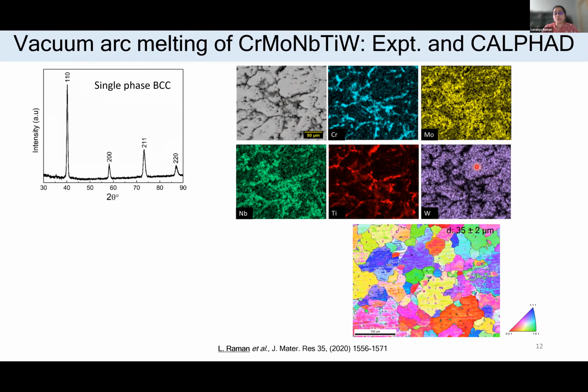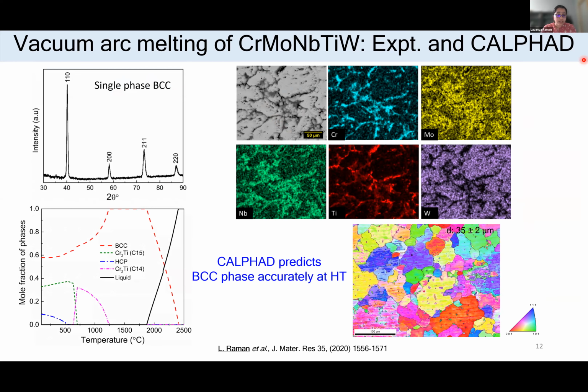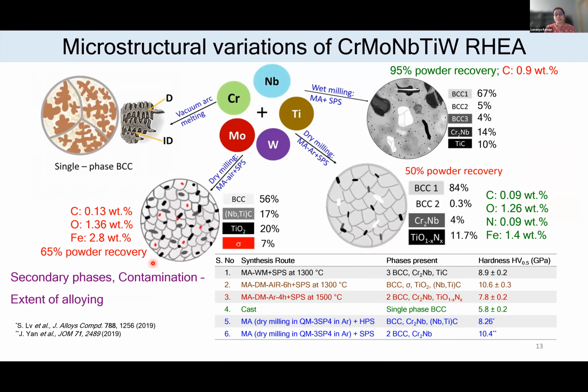So here, tungsten has the highest melting point, so that goes into the dendrites. And then moly and niobium go to the interdendritic region, and the last to solidify will be chromium and titanium. So the single phase nature of this alloy is confirmed using EBSD. And when we did the CALPHAD studies, this also shows that at high temperature, we have only a single phase BCC.